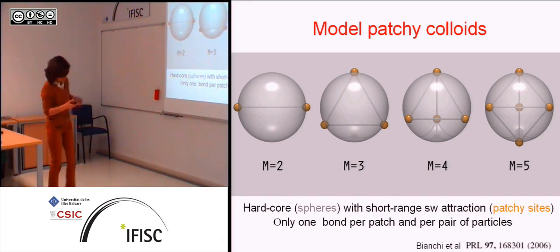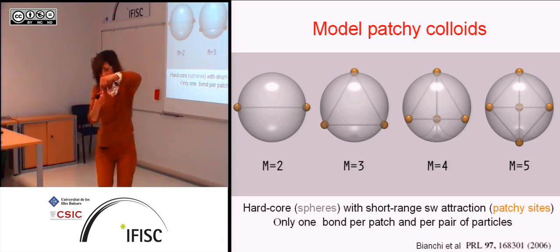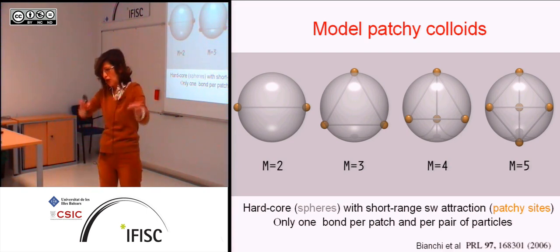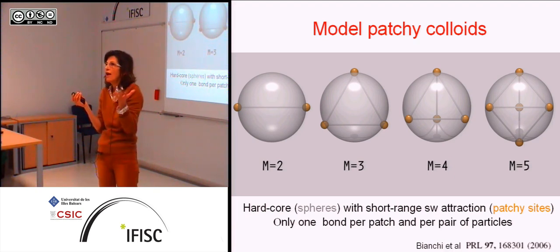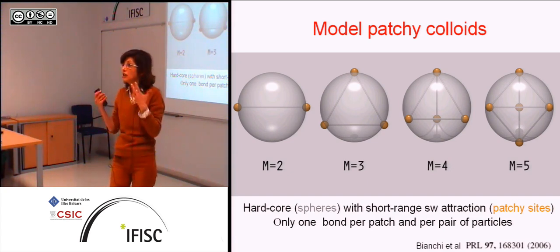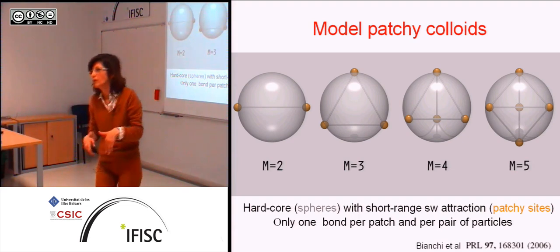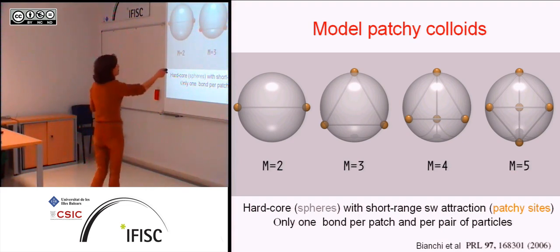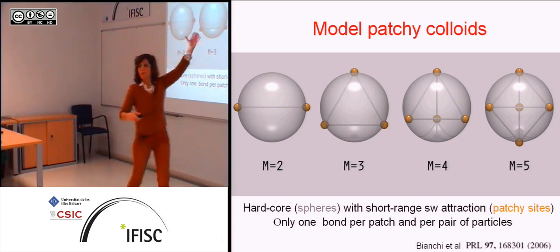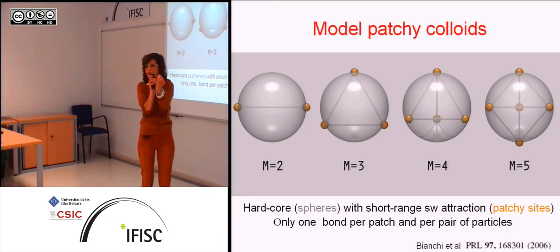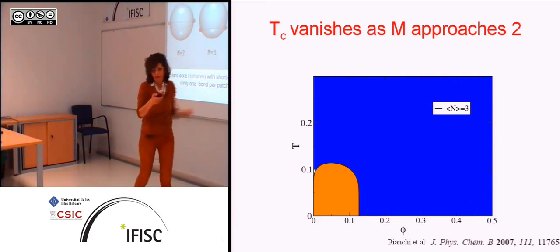And what Sciortino, remember that I said, if you only have 2 spots you form chains, even if the chains are off lattice, basically there's no energy left to condense. So chains, in that sense, have no attraction. If they're flexible, they don't even order into these liquid crystalline phases. So basically, we know in the chain limit, the critical temperature has to go to 0, if there is a critical temperature. We also know that if you put too many spots, this becomes more and more isotropic as you put more spots. So you can imagine that after a number of spots, you get something like the Ising type of phase separation.